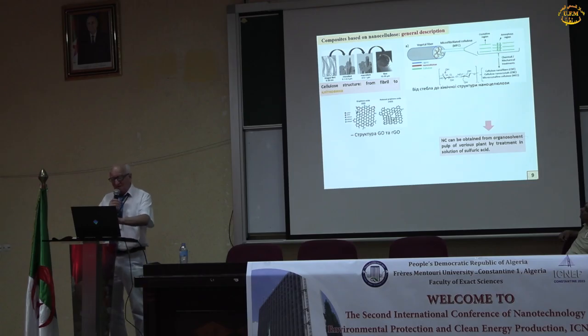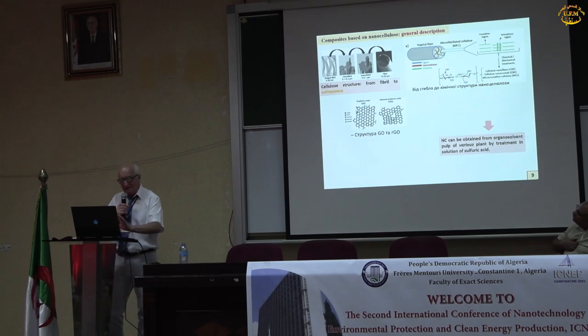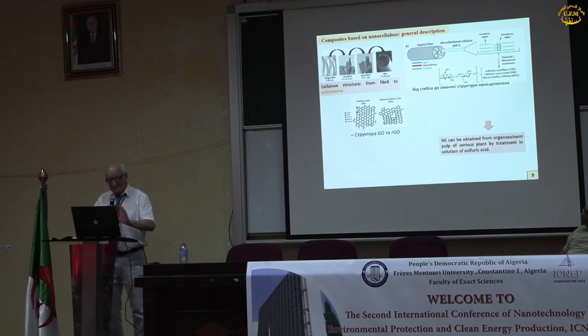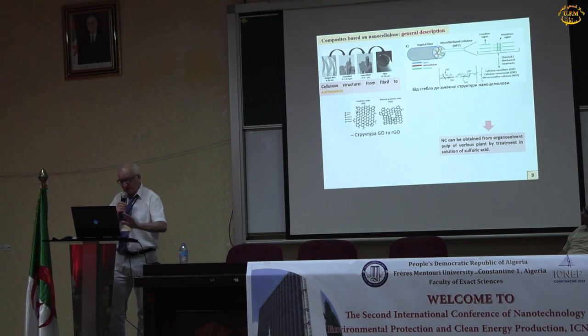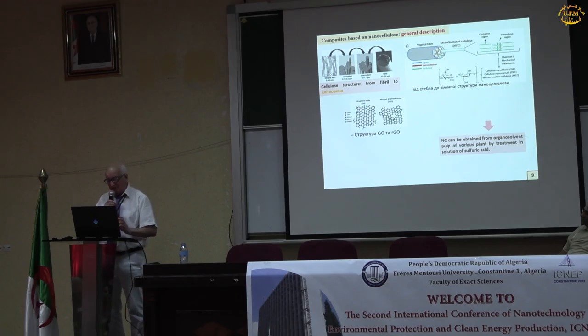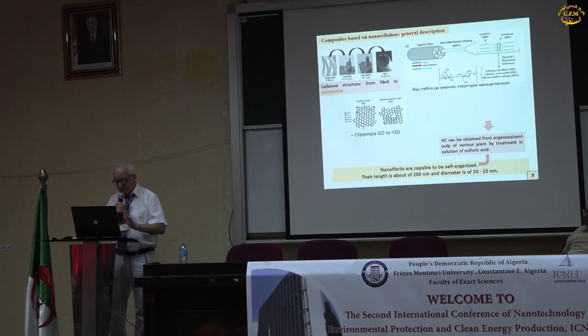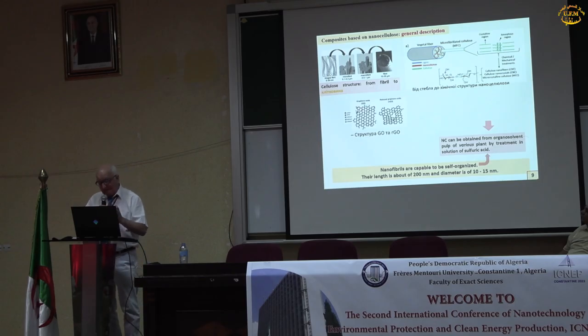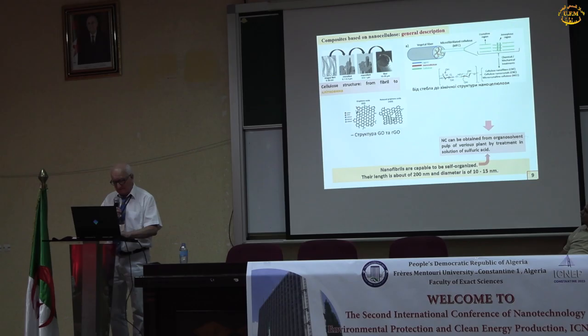Here you can see a description of the cellulose structure, from fringed fiber to microfiber to macrofiber to the fiber of the plant. You see some description of the structure in the Ukrainian language also. We see the structure of other components of the composite, graphene oxide and reduced graphene oxide. Nanocellulose can be obtained from organosolvent pulp of various plants by treatment in a solution of sulfuric acid. Nanofibrils are capable of self-organizing. Their length is about 200 nanometers and diameter is near 10 to 15 nanometers.